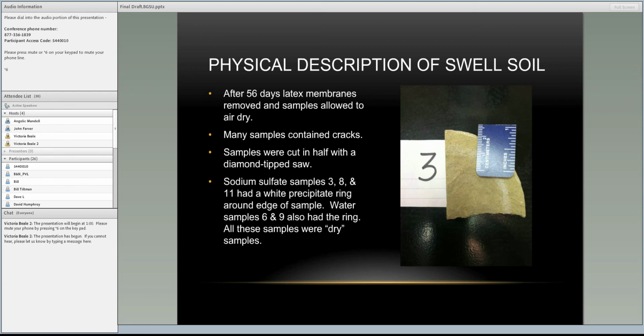And so we wanted to focus in on some of this white precipitate that we were seeing on the SWELL samples. Like before with the stabilized soil, where we really focused in on that white precipitate, we did the same thing with the SWELL samples, hoping to find ettringite or gypsum. And what we found was the white precipitate is primarily calcite. And so this is an XRD scan down here showing a sample from 730 and showing the calcite peaks.